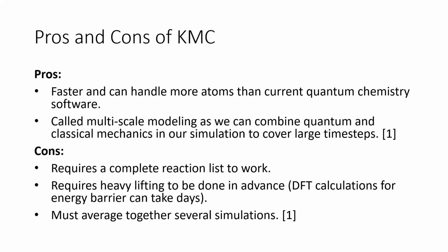So this allows us to cover huge time steps, whereas classical simulations can have time steps of picoseconds, if we're lucky. Here we're talking about milliseconds in our time steps. So that allows us to run simulations covering about 20 seconds of deposition or greater. This would be impossible with classical molecular simulation packages.